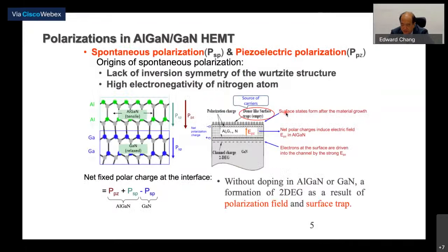So this gives you the idea how the material can have high current without doping. The GaN material is basically formed by high band gap AlGaN and low band gap GaN. So the material lacks inversion symmetry over the wurtzite structure, so that creates an electric field within the material. And this is because of the high electronegativity of nitrogen atoms.